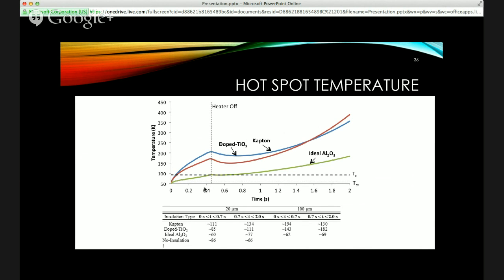So when looking at the hotspot temperature, there's a line missing. But due to the fact that I had a higher than normal transport current, as well as the heater, the temperatures are slightly higher than what you would normally see, just so we can see a difference. But you can see that the higher thermal conductivity is already resulting in a lower temperature between the doped titanium and the Kapton. The doped titanium is the red line, and the blue line is Kapton, the Kapton insulated coil.